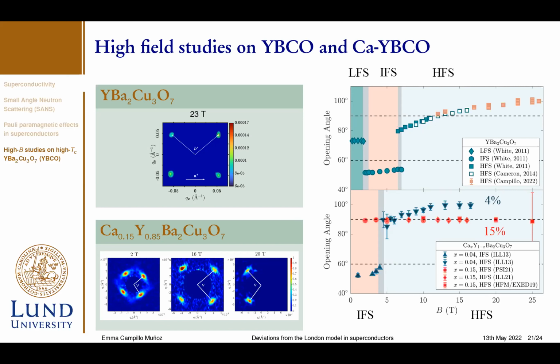However, another experiment was done before on a 4% calcium doped YBCO sample, and we see a similar transition between the intermediate phase and a high field transition, in which the behavior is actually the same, and the structure is also stabilizing at 100 degrees, but the whole diagram is shifted by a factor of 2. So we think that when adding calcium, and therefore changing the hole concentration, we are actually changing the phase diagram, or the vortex lattice behavior along field.